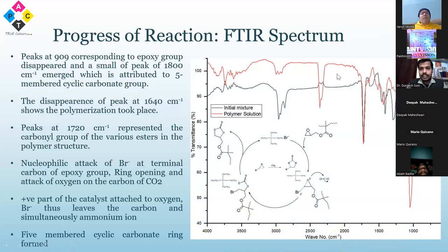Like in this figure, we can see this is the FTIR spectrum of the polymer. In this reaction, at 909, it is corresponding to the epoxy group. And at 1800, it is corresponding to the cyclic carbonate group.